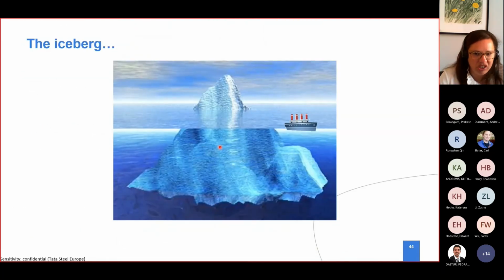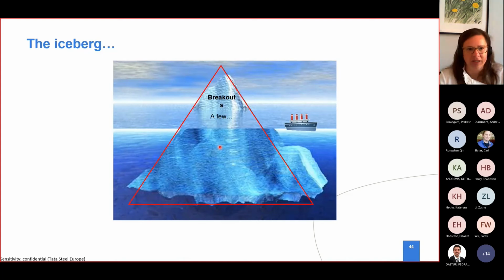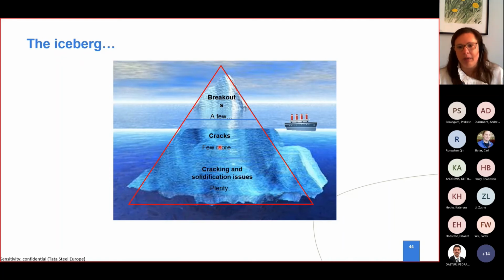But why is it so important in the process, where I am talking so much of the formation and thermomechanical properties? Because when things go really wrong and the thing breaks out, a breakout is only the tip of the iceberg. It breaks out when it really goes wrong, but it already goes bad when we have cracks. So first cracks, and then it breaks out. Luckily, breakouts are really few on a regular basis. Cracks, well, we have a little more than breakouts. But the cracking and solidification issues and all the things behind are even more.